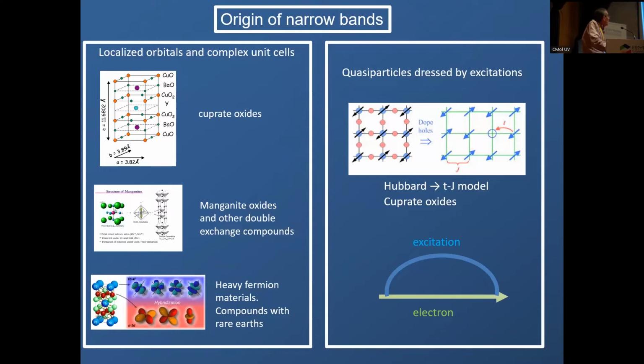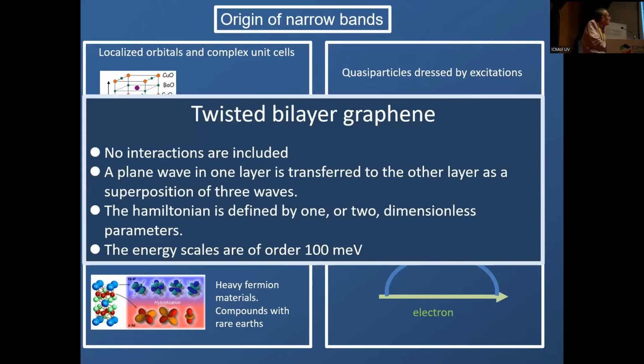And in that respect, I want to emphasize that in these better studied strongly correlated systems, these flat bands come, on one hand, as I said already, because they are derived from highly localized f orbitals in uranium or cerium or whatever. And in addition, the bands become even flatter because, as these systems are close to magnetic transitions, the electrons are dressed, they have to drag along, carry along magnetic excitations, and then they become even heavier. That's why you have narrow bands in heavy fermion systems.